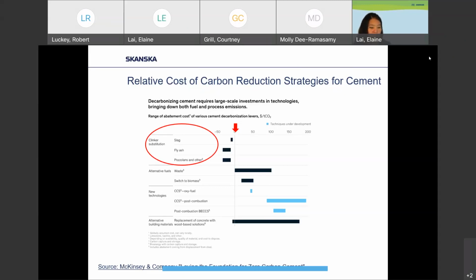So what we see is that substituting out cement with what they call SCMs, or supplementary cementitious materials, these typically are waste products from other industrial processes, but are a great substitute for cement. Other options that are coming on the market that we're just starting to see include glass pozzolans. So this is from recycled glass, but the most typical SCMs or substitutes for cement include slag and fly ash.